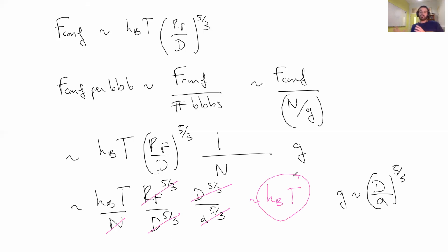Blobs are independent objects, and inside a blob, well, the free energy is kbt. We already recovered that when we were dealing with the free particle in the quantum box that was mimicking a polymer chain. And we calculated typically the free energy inside, and we found that the free energy of the full chain is kbt. Because the blob, in the unconfined situation, was the full chain itself, and it has a typical free energy, which is kbt.